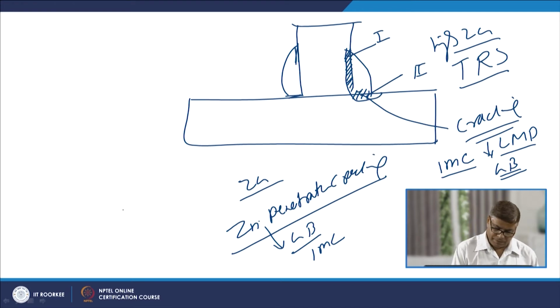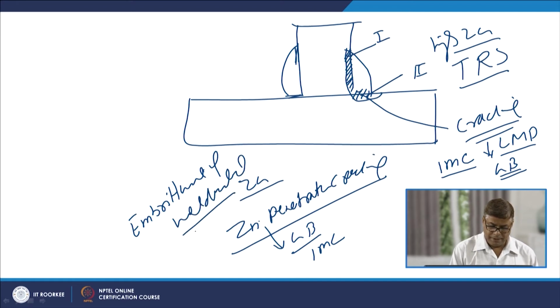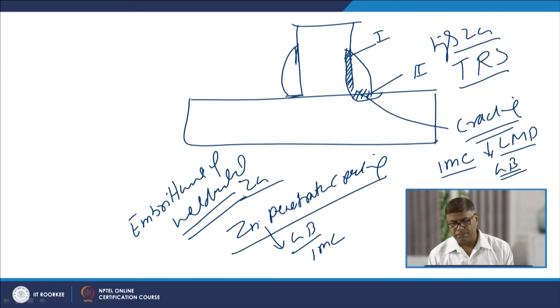So, apart from the cracking, IMC formation leads to the embrittlement of the weld metal. So, this is one typical problem associated with the zinc, when zinc is getting mixed with the molten metal and leading to the formation of the intermetallic compounds.